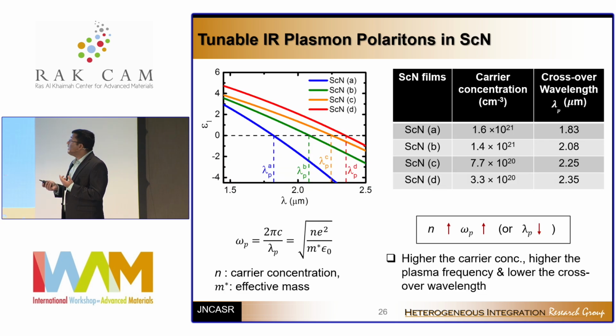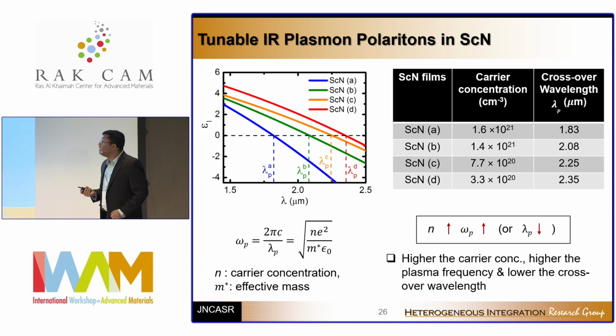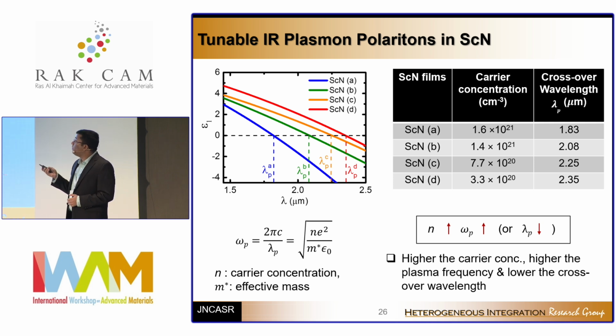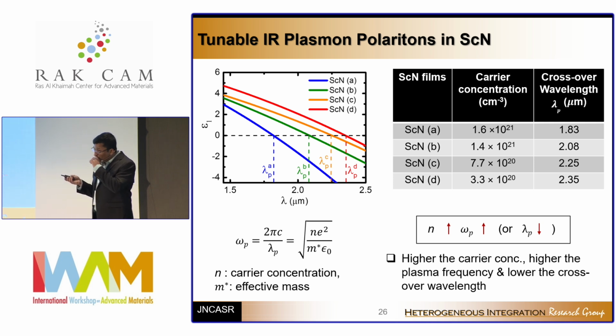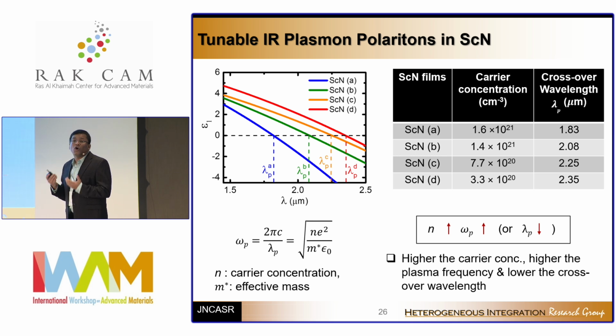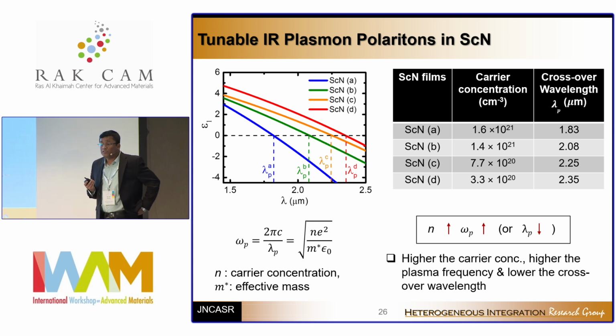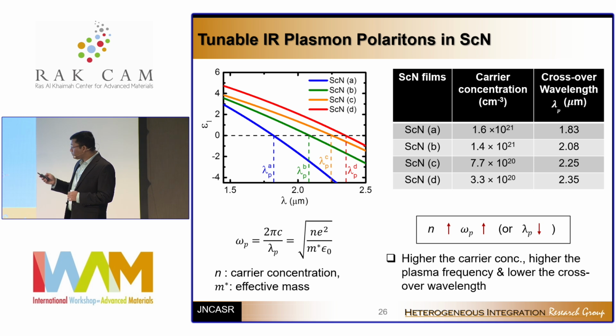Now, one of the things is that metals generally don't allow you to change carrier concentration that easily, but a semiconductor does, by doping. So just by changing the doping concentration, we can shift the plasma frequency or the ENZ frequency from 1.8 micrometer to around 2.3, 2.4 micrometer. So this pretty much covers the short wavelength infrared spectral range, which is technologically extremely important because a lot of security applications use this spectral range.